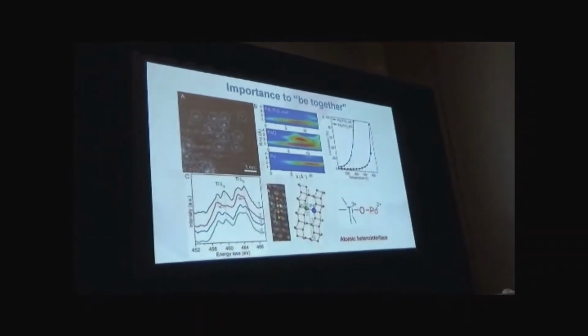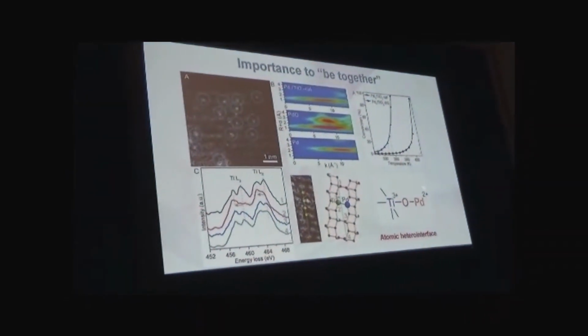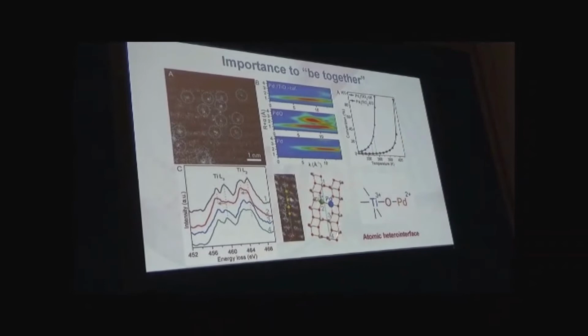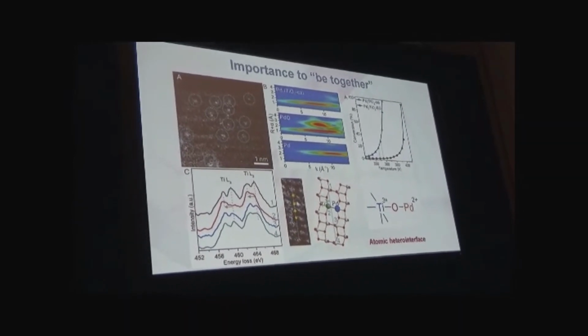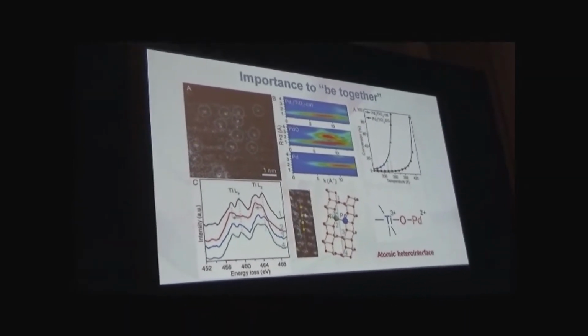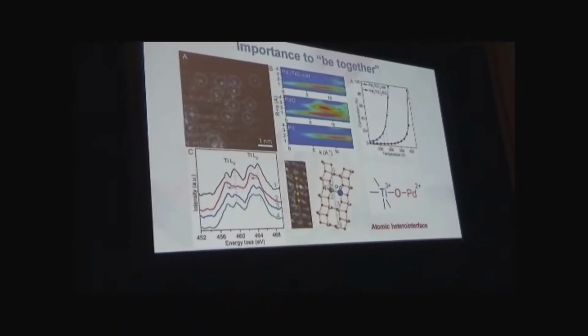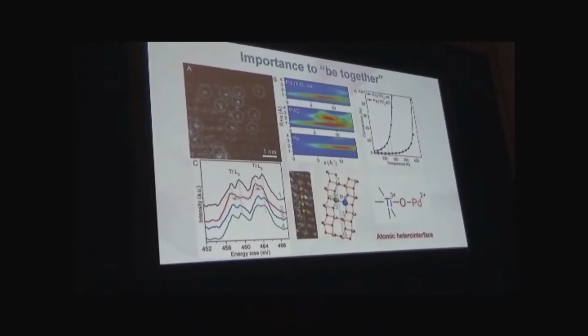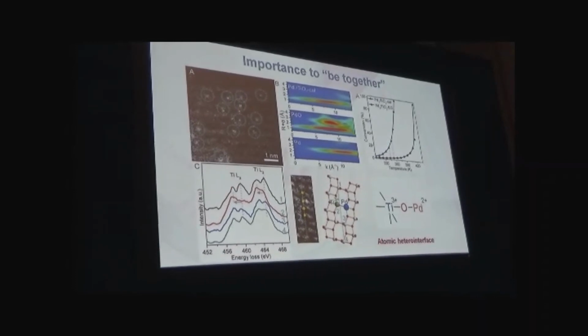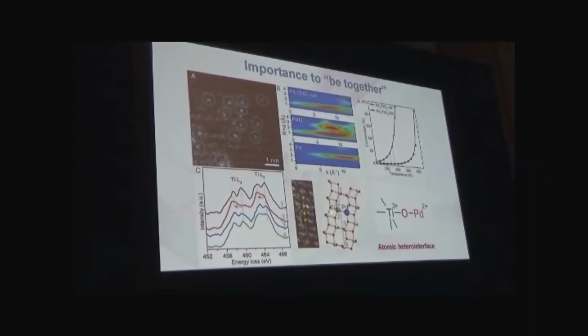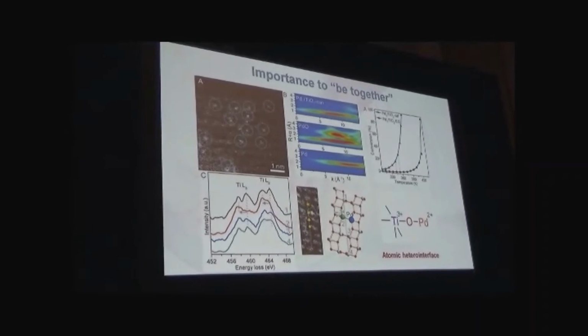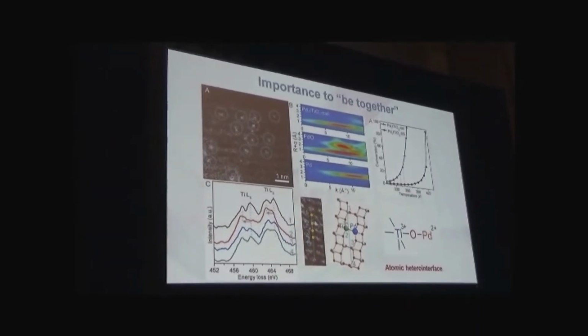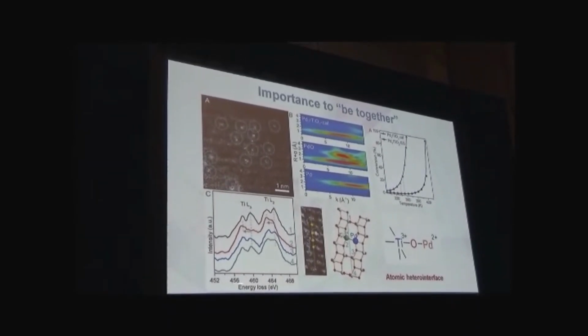In the previous example, we demonstrated the electron will transfer to the titanium. With the cascade, we can make such an interface. Here is the HRTEM. Because it's photo-induced, the radical would make plenty of oxygen bonds and the electron transfers to the titanium. So after catalysis, we can make titanium 3+ and palladium interface. Here's the energy loss.